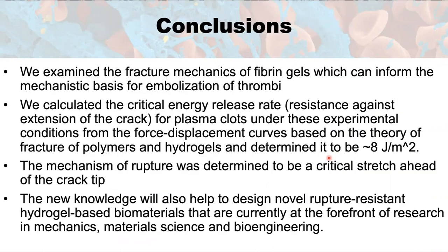So in conclusion, in this paper, we were able to examine the fracture mechanics of fibrin gels, and this can be used to inform the mechanistic basis of embolization. We were able to calculate the critical energy release rate from experimental curves and then compare them to a theoretical model, and determine that the theoretical model is a good approximation for what we're seeing experimentally. We determined that the mechanism of rupture is a critical stretch that occurs ahead of the crack tip. And then ultimately, in future work, we can potentially use this new knowledge to help develop rupture-resistant fibrin-based hydrogels, or to inform better treatments for thrombosis or embolization as well.